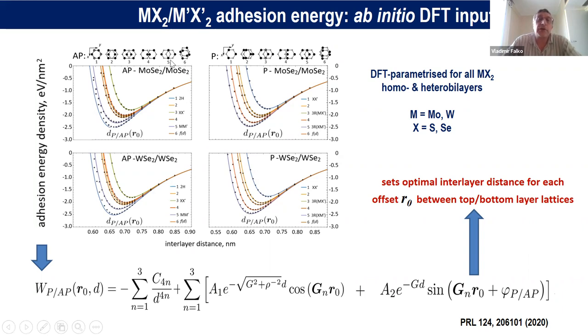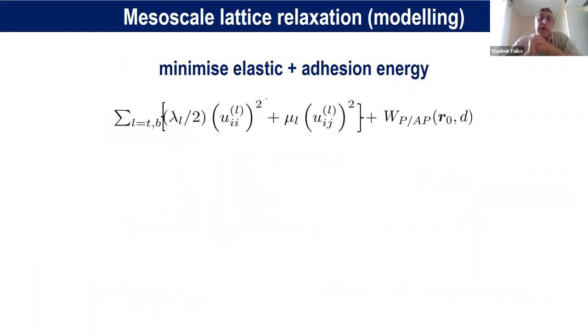And what we also did in this analysis, we calculated energies for actually multiple ways to offset one layer with respect to the other to obtain the analytical expression by interpolation, which allows us to describe the dependence on the interlayer distance for any arbitrary offset of the atoms in the top layer crystal with respect to the bottom layer crystal. Why do we want to do that? Because for small angles of misalignment, the local stacking of the two layers varies slowly at the scale of the lattice constant.